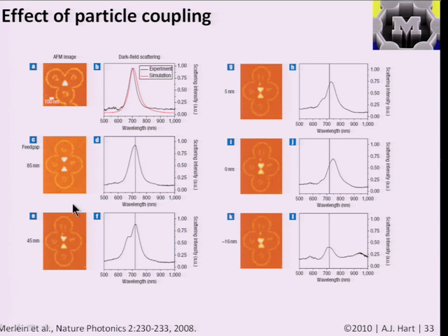And I think here they're using the spectrum for an isolated particle as a reference, and you can see that in relation to the general effects we've talked about, the effects of dipole or quadrupole resonances and shape and spacing, the spectrum is very different based on how much space there is between these 2 particles. And then the intensity of the spectrum drops down quite a lot when the particles touch, indicating that this gap, this very small gap between 2 very sharp features, is a zone of very strong enhancement.